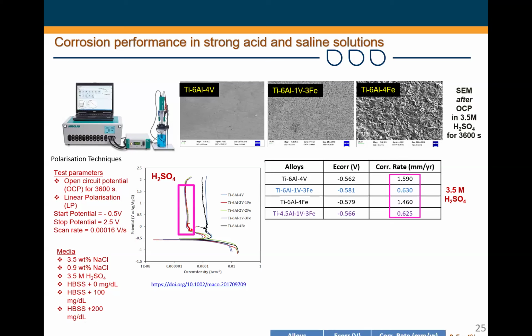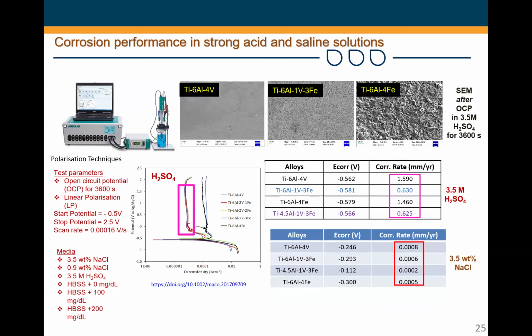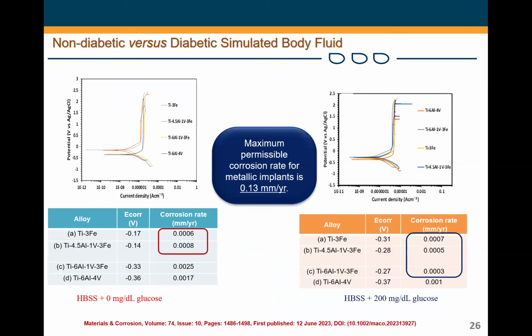And we didn't end up here. We then looked at 3.5 weight percent NaCl, which is also too extreme when you compare to physiological solution. And here, of course, you expect titanium to be happy in this space, regardless of how much iron you had, whether you do partial or total replacement of vanadium with iron, the corrosion rates seem to be similar. And then that gave us the confidence to move forward and test in physiological solution. And we tried to do all of this in vitro. So it's not in vivo, it's not in a human being.